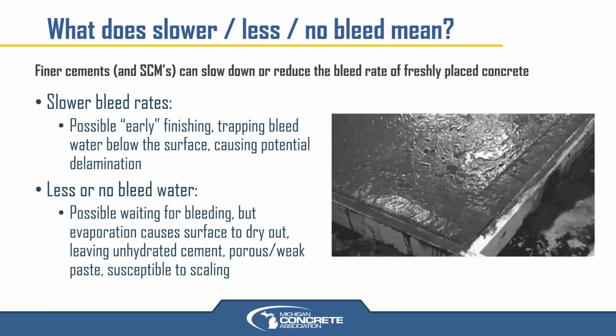It's rare to find, especially with type 1L. And even prior to that, I have not seen a lot of projects that bleed unless they, for some reason, had a very high water cement ratio. But we did have a photo from our files that I pulled. You can see this slab, it has the water on top. Like it wasn't there originally when this slab was struck off, and looked like it's even been edged along those forms. You can kind of see that line. So that's already occurred, but that bleed water is showing up on the surface, kind of puddling. Looks like it puddles up on the surface. So the photo is a classic example of bleeding.